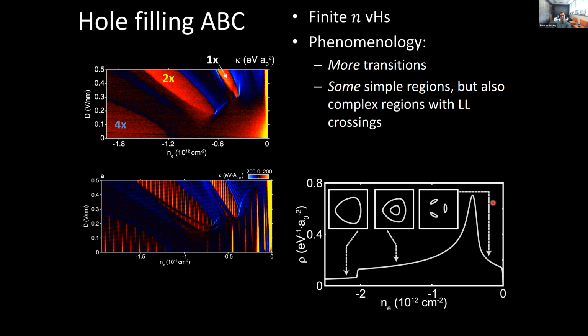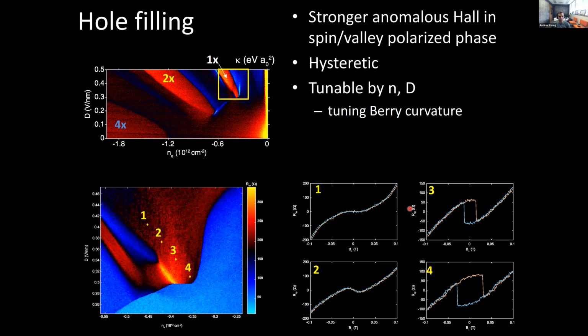So in particular, you have much more strongly developed threefold pockets. The Van Hove singularity, where the density of states becomes very large, is at finite density, and then you have this transition between a simple Fermi surface and an annulus. And so you can try to work this out. This also seems like there are just stronger features on the hole side, stronger, interesting phenomenology.